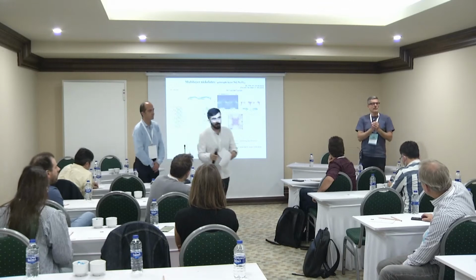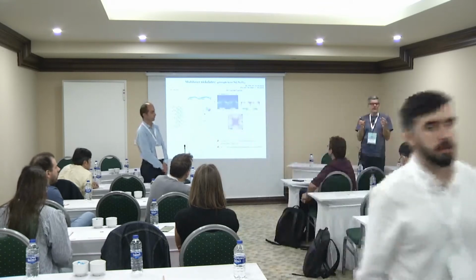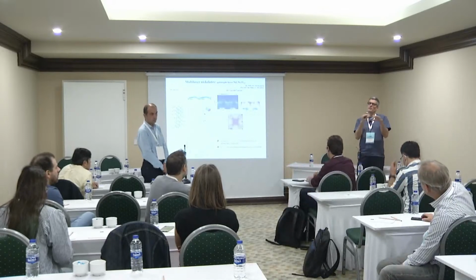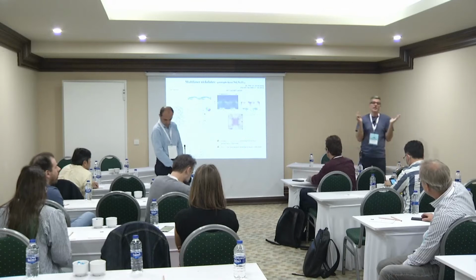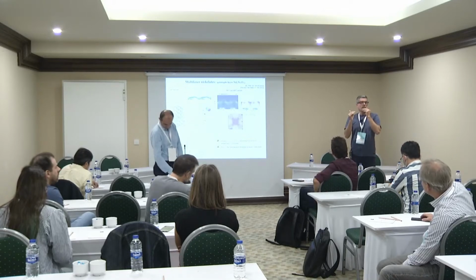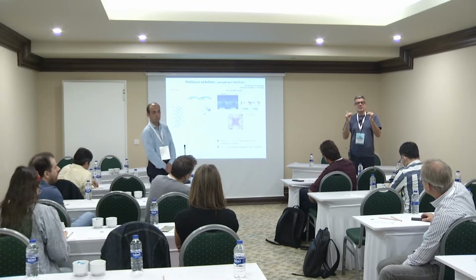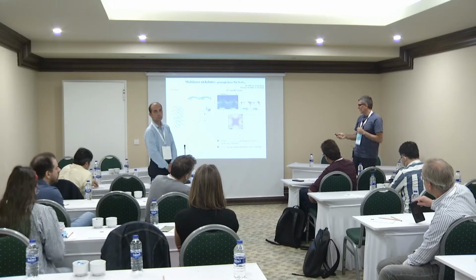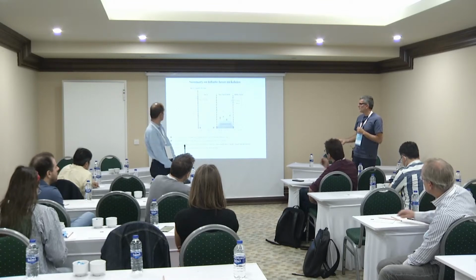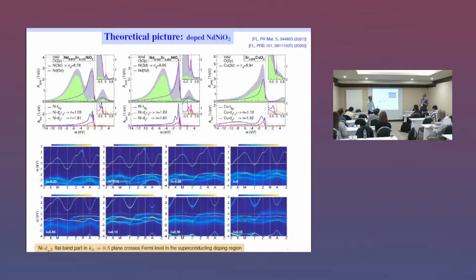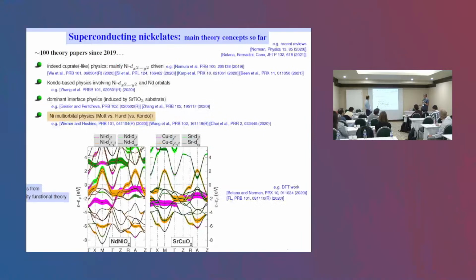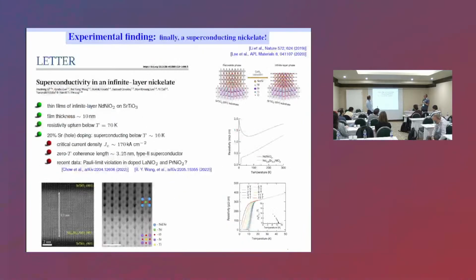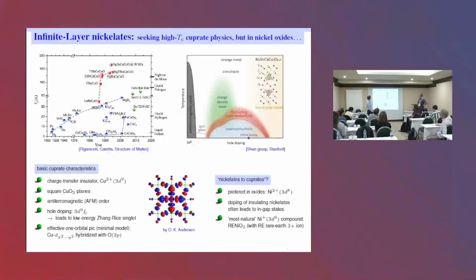That I think I would agree on, and really putting a finger on the charge transfer physics we have in cuprates, which I think is very, very important, and that has been a bit put under the rug, especially, I have to say, from theory, by putting it on the Hubbard model level. Well, you can do the Hubbard model, but you always have to be aware the lattice is not copper, but copper, oxygen, copper. So there's the oxygen between, and we have taken out this oxygen very quickly and said it's like a one-band system, and it works, but maybe for some accidental reason it works.